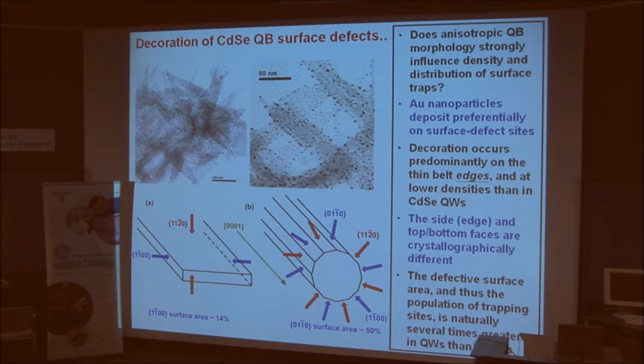I think, I may not be right, but I think this is the first time the strategy's been applied to nanostructures. And so we carefully deposited gold nanoparticles on the belts. And to our surprise, we found that they are deposited almost exclusively along the thin belt edges and not on the broad top and bottom surfaces, which is to imply that most of the defects are along the thin edges of the belts rather than on the top and bottom surfaces. And that gives one possible explanation for the better optical properties of the belts, because these apparently defective thin belt edges make up only 14% of the total surface area, whereas they would make up on the order of 50% of the surface area on a cylindrical wire.